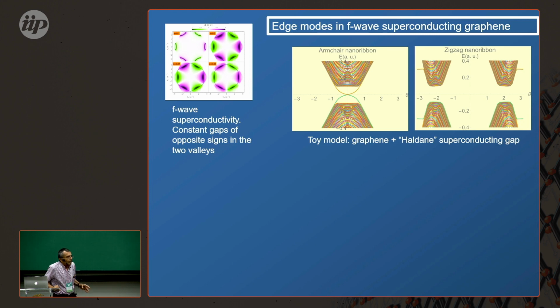As I said, it's not s-wave in the strictest sense. It turns out that if you make calculations for superconductivity in a kind of graphene quantum dot, depending on the termination of the quantum dot, you have mid-gap states or not. These mid-gap states are combinations of electrons and holes.